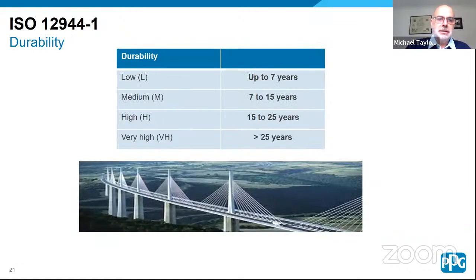In terms of durability, the ISO 12944 Part 1 lists 4 durability levels now. Low durability is up to 7 years, medium 7 to 15, high 15 to 25, and very high durability is greater than 25 years. And they suggest that durability is the time from coating up to when major maintenance is required. They use the ISO Ri3 corrosion scale to give that limit. So when 10% of the area has reached Ri3, it's considered that you would need to do major maintenance. Durability is not the same as guarantee.